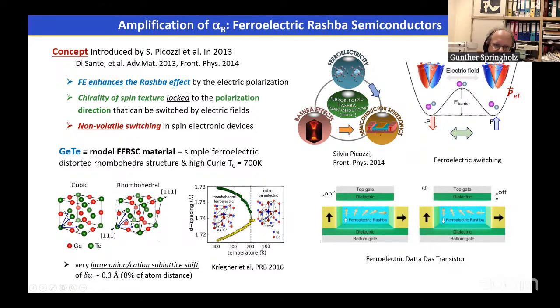So here on this diagram is shown the in-plane and out-of-plane lattice parameter of the system. In-plane means perpendicular to the 1-1-1 direction, and out-of-plane parallel to the 1-1-1 direction. And one can see at a temperature of around 700 to 750 Kelvin, there is a structural transition from a cubic to a rhombohedral phase. The cubic phase is paraelectric, and the rhombohedral phase is ferroelectric. So the TC is very high, well above room temperature. And in addition, in this system, there is a very large shift of the anion and cation sublattices of the order of 0.3 angstroms, which is about 8% of the interatomic distances in the system. So it's a very large effect.